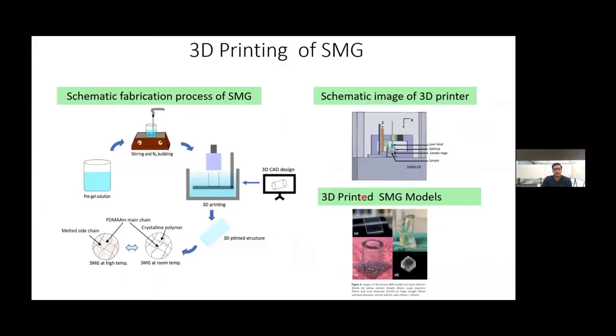Here is the fabrication process of a shape memory material. At first, we make the precursor solution by mixing all the monomers, crosslinkers, initiators, UV absorbers, and stir it for 10 to 15 minutes with continuous supply of nitrogen bubbling. And then we use this precursor solution for 3D printing. This is stereolithography. And for this 3D printing process, we have used this 3D printer. We call it Swimmer. And using this 3D printer, we have made these models like this finger shape and hollow cube shape.